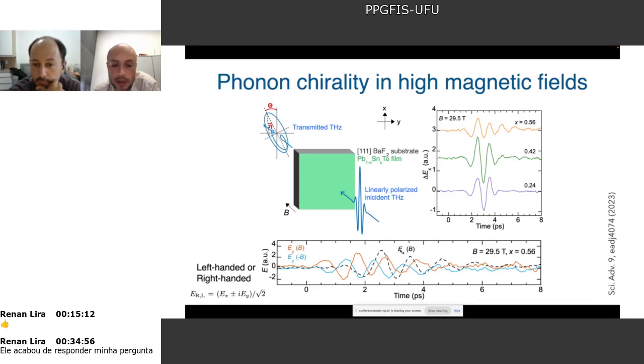You can see it here. EX, the transmitted along the same direction of incidence, here in black dashed line. And also, if I change the polarity of the magnetic field, then EY also changes, becomes the opposite of EY for B. It means that with the application of magnetic field, the phonon becomes chiral, and then the light that was linearly polarized becomes elliptical, right? I can combine these two components, X and Y, like this, EX plus and minus i EY divided by the square root of 2, and then I will call this left-handed or right-handed.